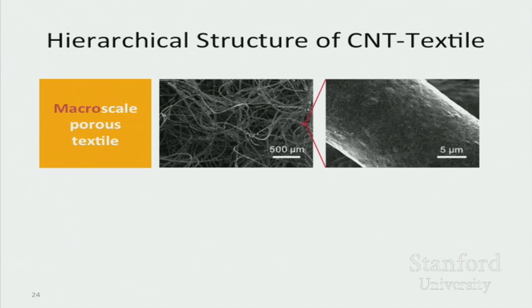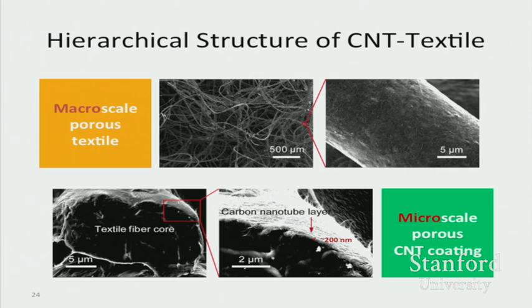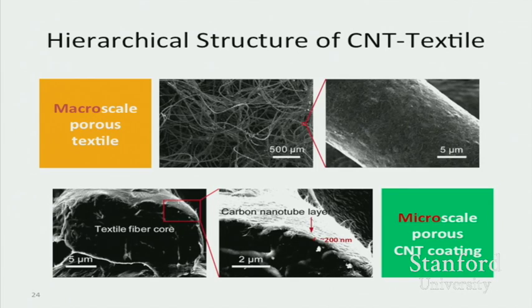So what you have right here, each of these textiles consists of a lot of fibers. On the fiber surface, a lot of carbon nanotubes coat it, forming a layer onto this fiber. Now this carbon nanotube network is so conducting that the whole textile becomes conducting. You can look at the cross section right here, these carbon nanotubes sitting right there. And when you look at this textile, this is a 500 micron scale bar, so there are a lot of big pores in there. Bacteria, microbes are about a micron in size. The pores are so much bigger than the microbe size. So the microbe can go in and stick onto the wall and grow on this structure.